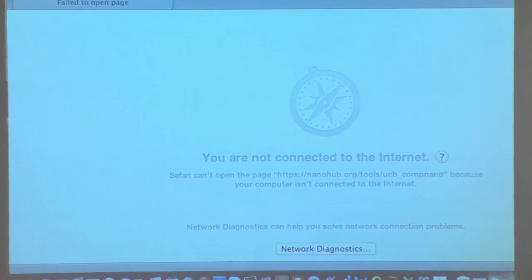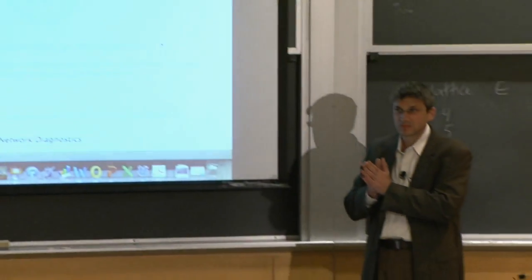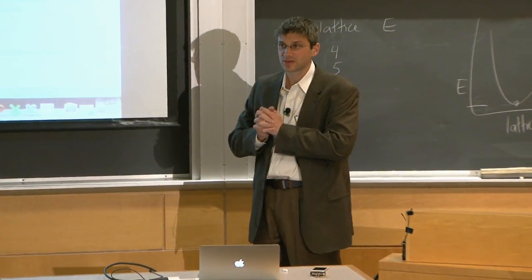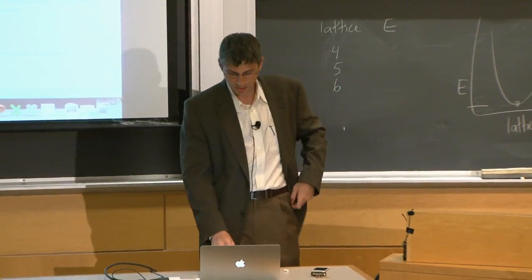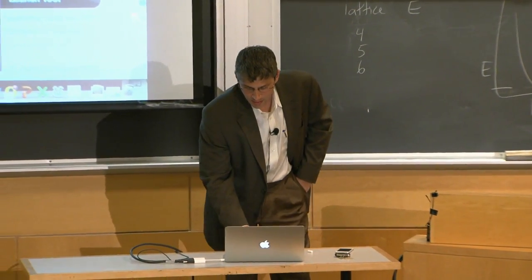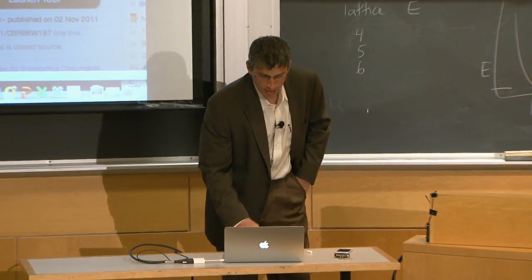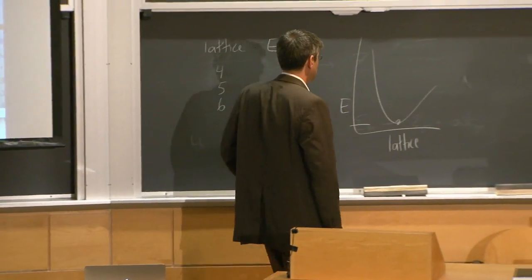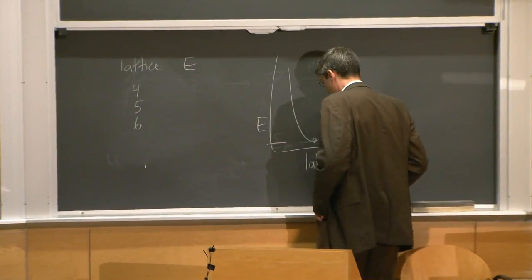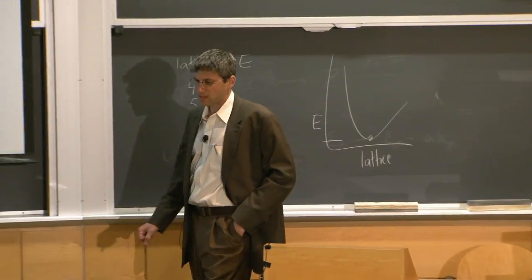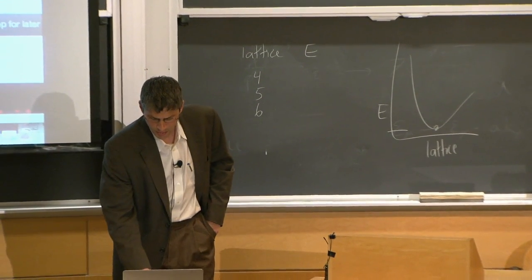So now, if I ask you how to converge the k points for the cohesive energy calculation, Sam, how would you do that? I would do exactly what I just did: change the number of k points and see how the cohesive energy changes. And what is the number of k points you need going to be for the atom? It should be pretty small.